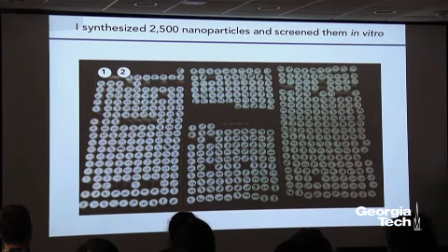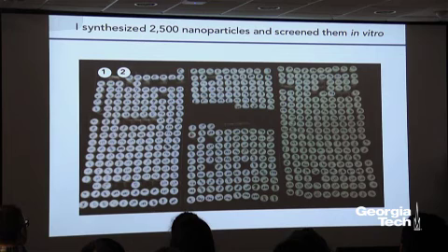This is what these things look like, though. We can make massive libraries quickly. And the thing I want to point out before I move forward is that for each one of these materials, when we actually turn this material into a nanoparticle, we include other stuff. We put PEG on the nanoparticle. We might put some cholesterol on the nanoparticle. The PEGs can have different molecular weights and different lipid tails. And for each one of these materials that we can synthesize, and again, you can synthesize up to 10,000 if you're Dan Siegwart, you can probably, as an honest scientist, formulate 500 variations off of that material by adding this cholesterol or that PEG or DSPC or DOPE or whatever. That's a conservative estimate. Okay, so we're getting into the millions and tens of millions of compounds that you could honestly ask as a scientist, hey, is this going to go to the liver, or is it going to go away from the liver, is it going to go to the spleen, is it going to deliver RNA to the heart, whatever.